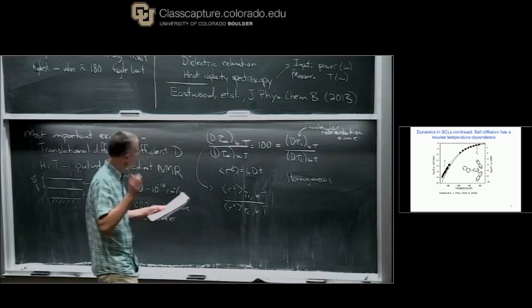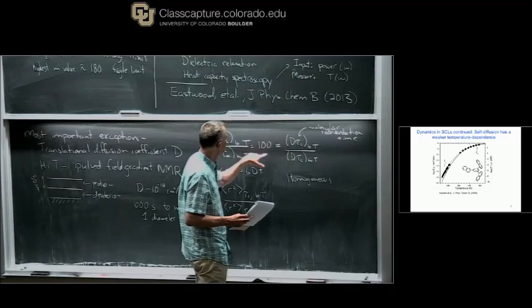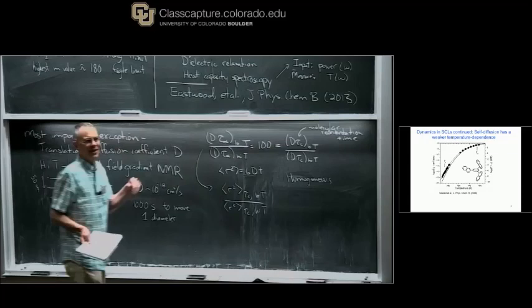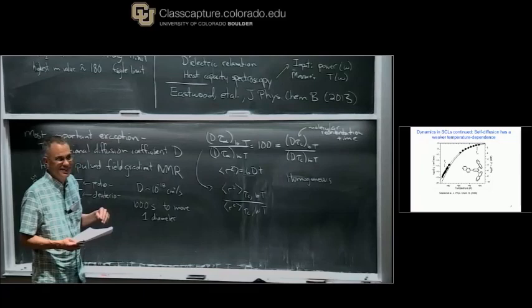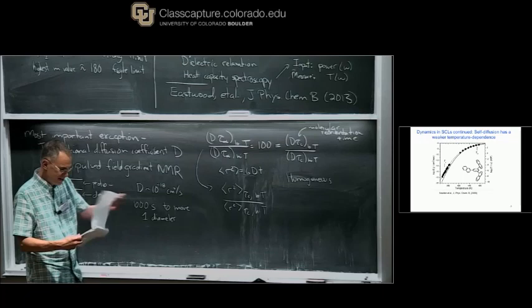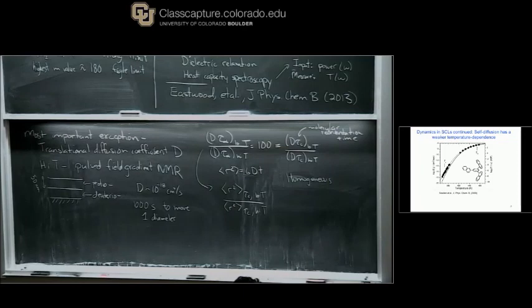One of the things we're going to talk about is how dynamics in supercooled liquids are actually quite heterogeneous — and that's what rescues you from this conclusion. This statement is still true on average, it just doesn't have to be true for any individual molecule. I would say I haven't seen a computer simulation that could show me that number of 100 is present — probably you would need something that has orientational degrees of freedom. This is another interesting point of contact between experiment and simulation.